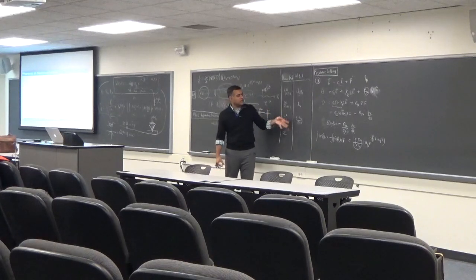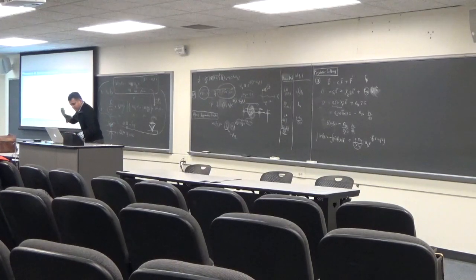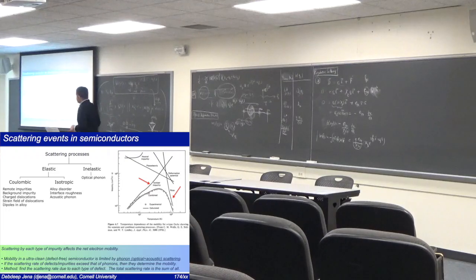Right now, for most semiconductors, you can do the numbers. The piezoelectric scattering, I think we had a little plot some time ago, and you can look at their relative strengths by looking at where they figure in this whole picture. So here's piezoelectric scattering, and here's the deformation potential acoustic phonon scattering. Around room temperature, the deformation potential typically wins out. But at low temperatures, the piezoelectric is actually the dominant one if you don't have impurities. The reason is that the Coulomb interaction stays independent of temperature. It doesn't care about temperature, right? If you do the numbers, that's where it ends up. So this is for typical semiconductors. Now you go to some other, crazier materials, then this can completely dominate.